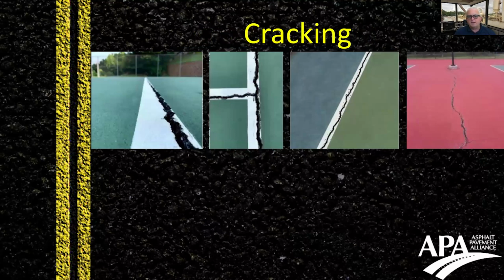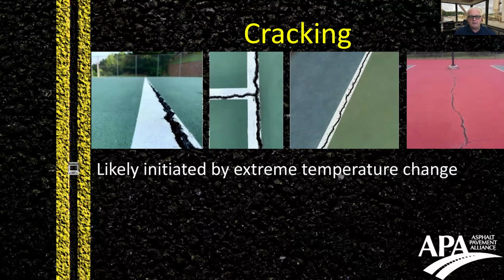Cracking is something that we work really hard with these surfaces to control. And it's not uncommon to see these types of cracks on sport courts. And they're often affiliated with the striping. Extreme temperature change is typically the initiator of these types of cracks.